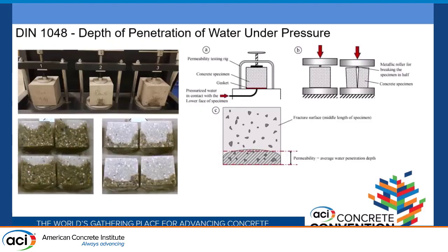So DIN 1048 is one of the methods that I really, really like, and it was absolutely common in Europe. It's tested on the cubes. You put concrete cubes, after 28 days, into this special device, and from the bottom there is water pressure for 3 days. And at the end of this test, you break the cubes in half, and you see what the penetration of the water is.